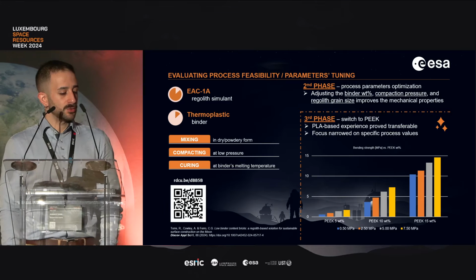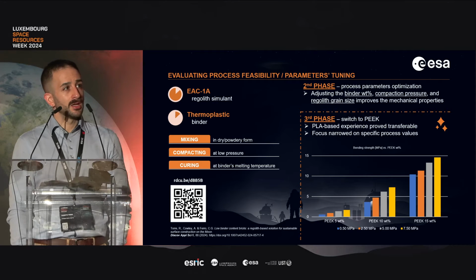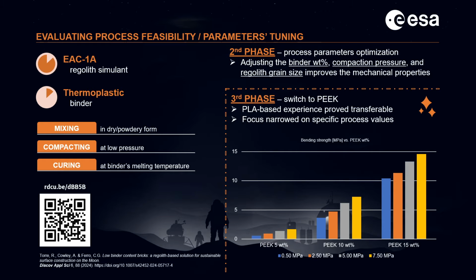As a third phase, we finally switched to PEEK, which is the final polymer that we would like to use. And we saw that all the experience we gained using PLA could be transferred. So that was a good choice. And we narrowed our focus to the specific process values that we saw were actually playing a role. You see here the relationship between the bending strength and the PEEK weight percentage for a different set of compaction pressures. To give you a reference, between 5 and 10 megapascal is what we would expect on Earth for a common cement. So we can really cover this purpose.